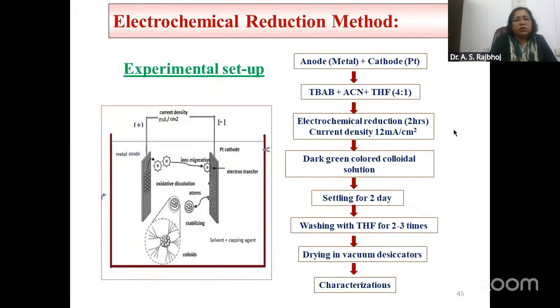Suppose we are using copper, so it releases copper ions. These copper ions migrate towards the cathode. After migration, they get discharged. As soon as they get discharged at the cathode, they get capped by the capping agent, which is tetrabutyl ammonium bromide, or tetraalkyl ammonium bromide, any of which you can take. Here we have taken butyl. So they are trapped by the tetraalkyl ammonium bromide, which is a surfactant, and the solution becomes colloidal, and it requires at least 2 days for settling. After settling, it is washed 2 or 3 times with THF, dried in vacuum desiccators, and then used for characterization purposes.